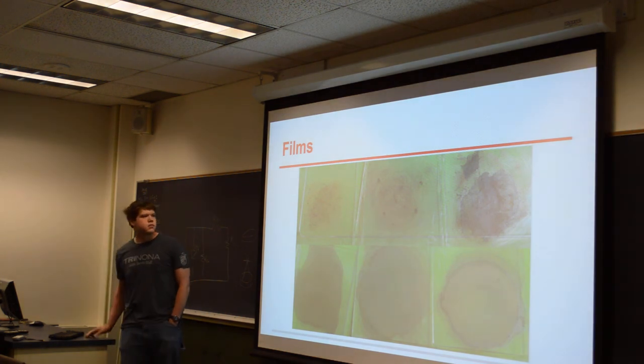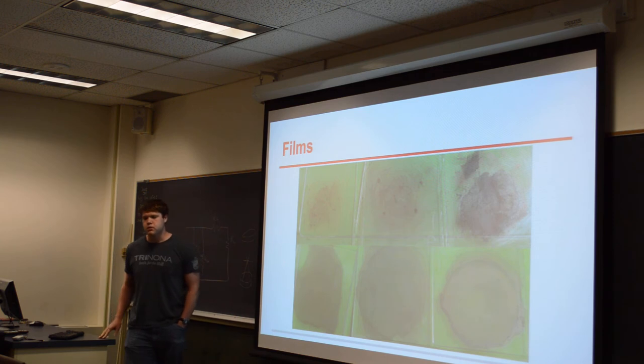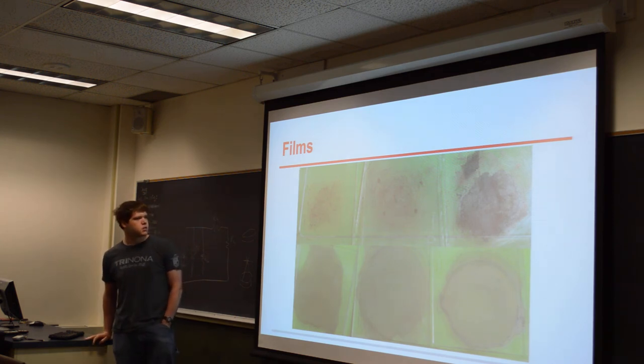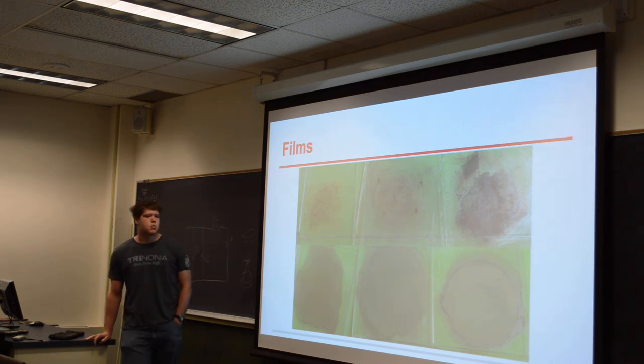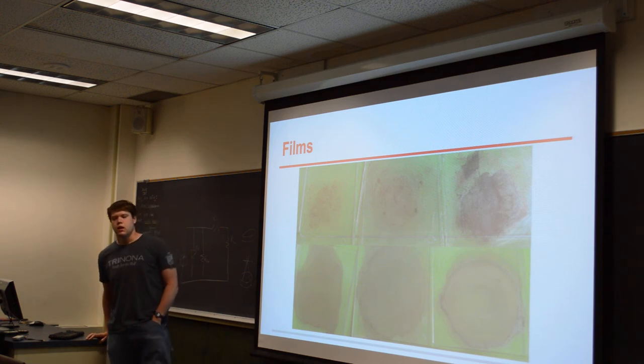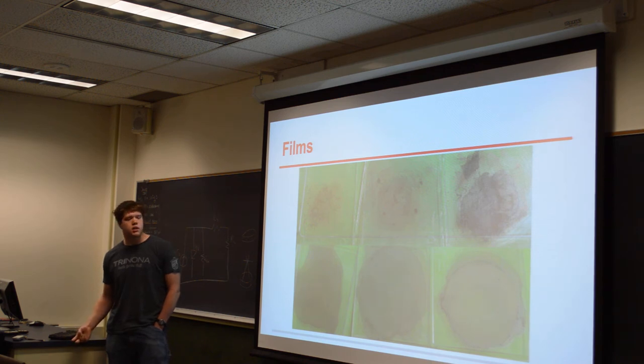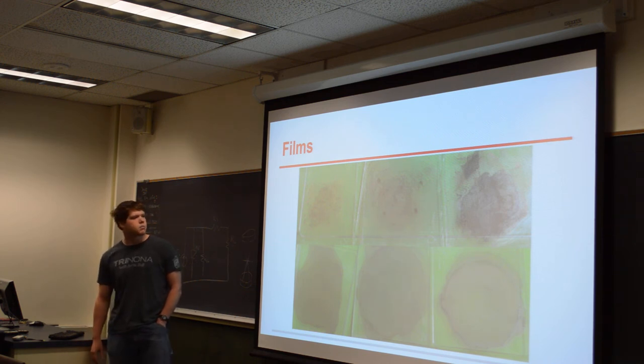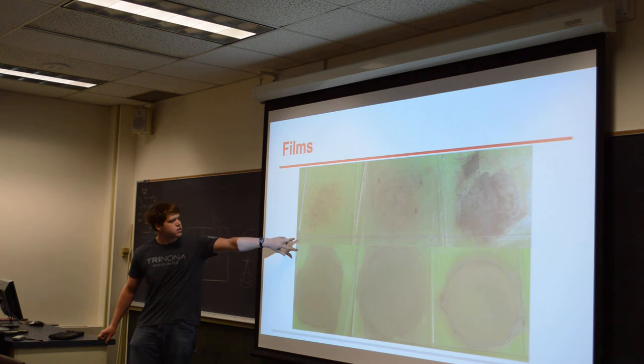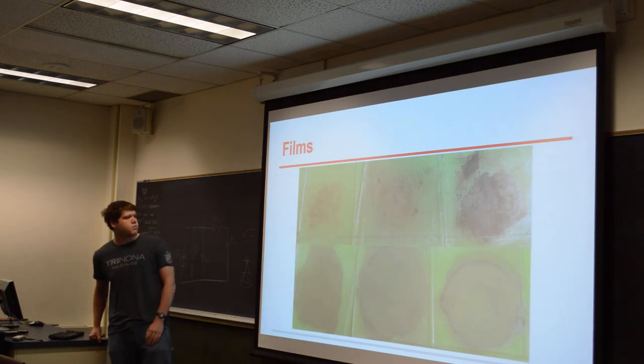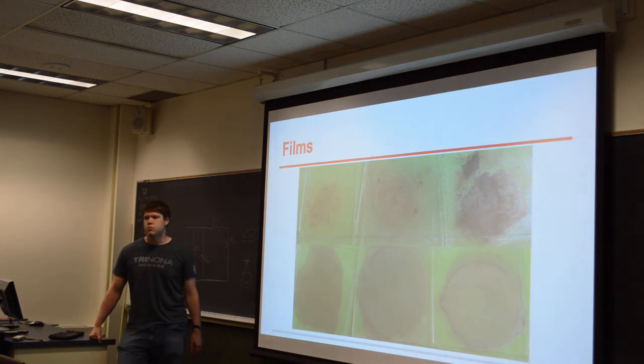After doing the experiments with the solvents, I also made some films of the nanocrystals. Three films were made from each of the samples. The first film was heated in air to allow it to oxidize. The second film was heated in nitrogen to control for changes from the heating but not from oxidation. The third film was not heated, just as a control. These would be the films that were heated in air, and they took on a much more golden color than the rest of the films after heating.